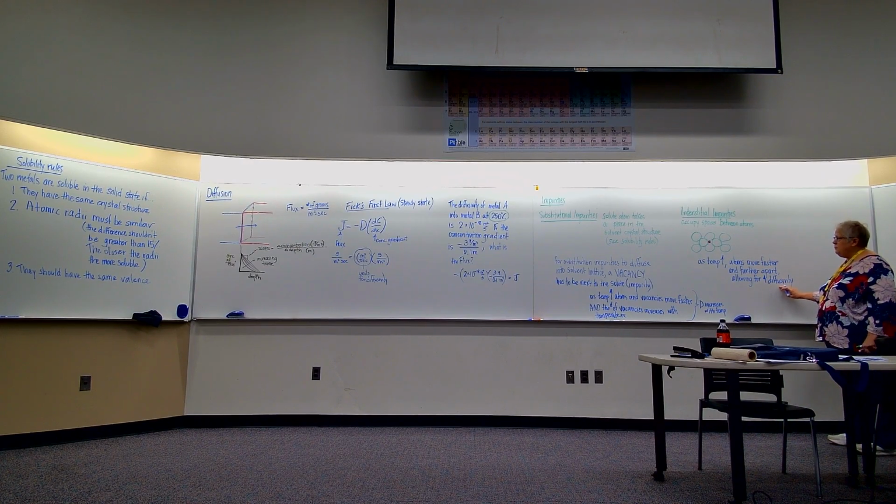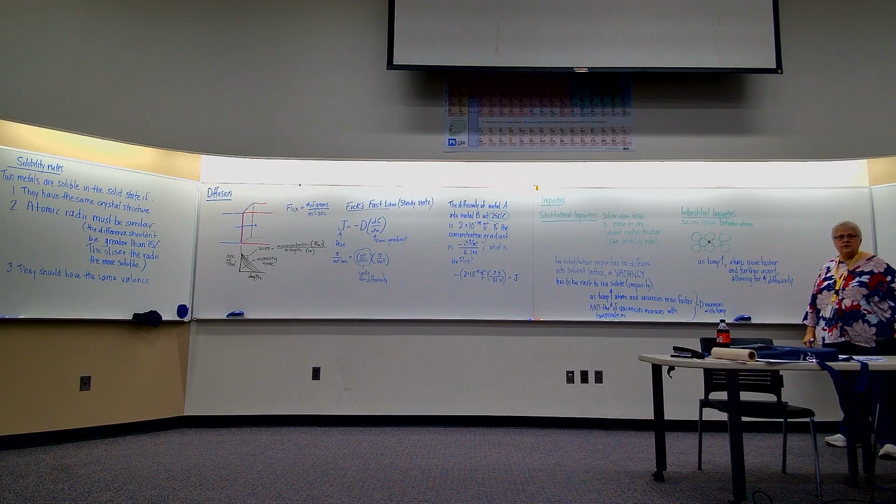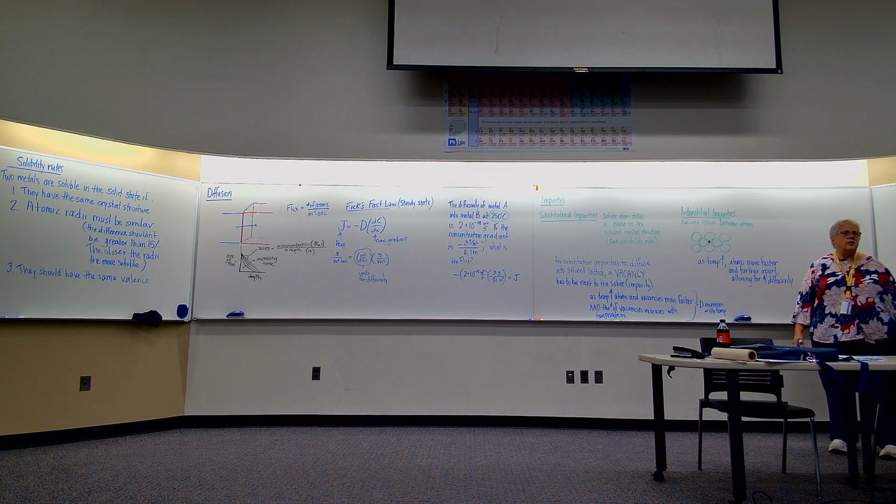Diffusivity increases with temperature for interstitial impurities, but in general, diffusivity is faster for them because they don't have to wait for a vacancy.